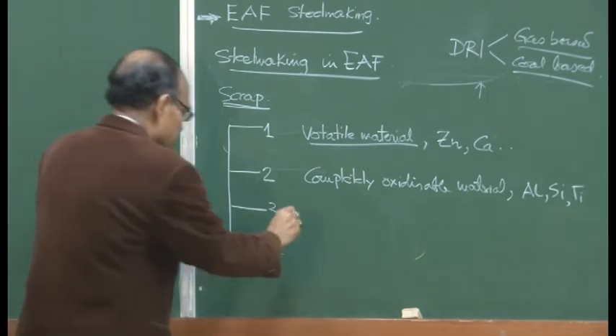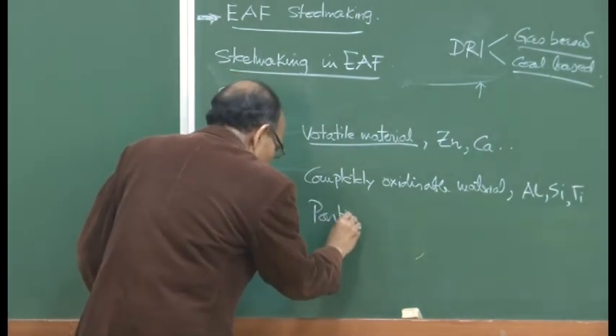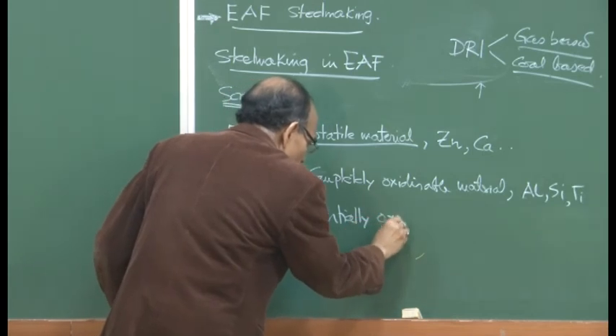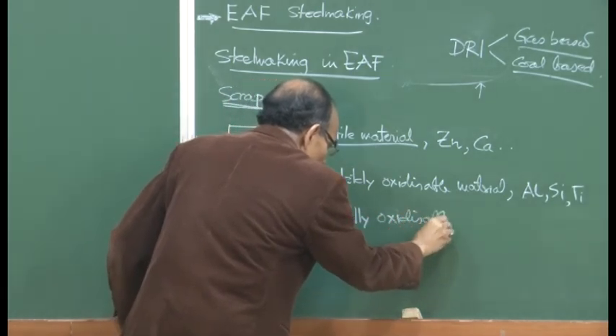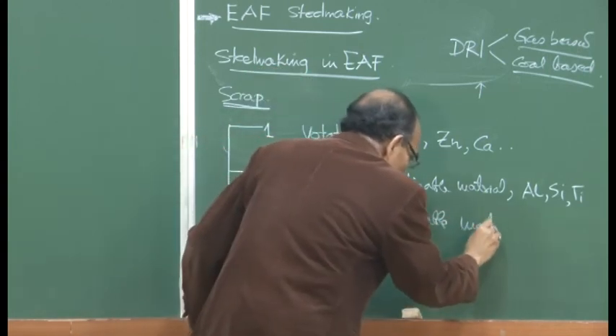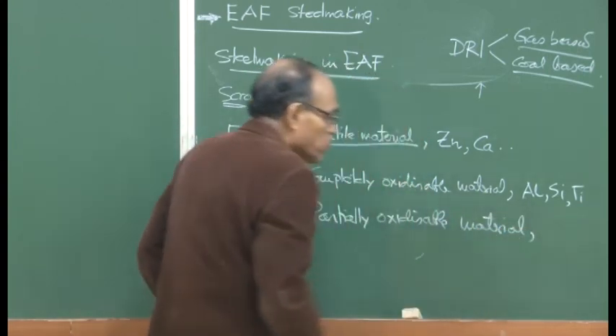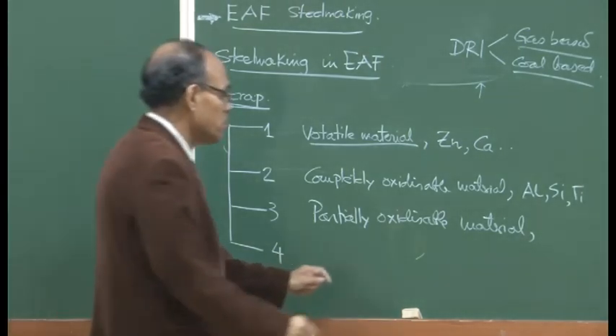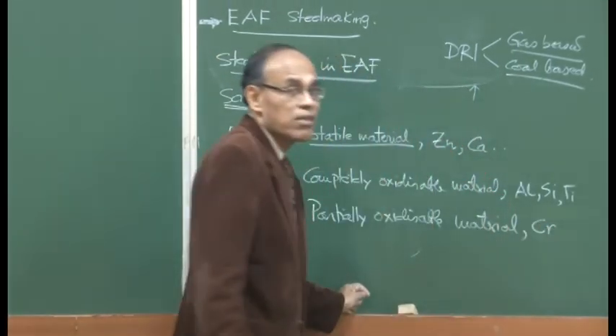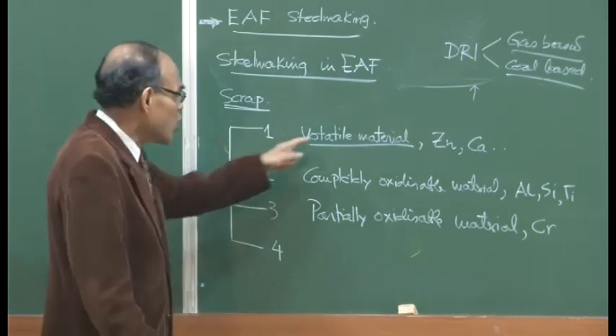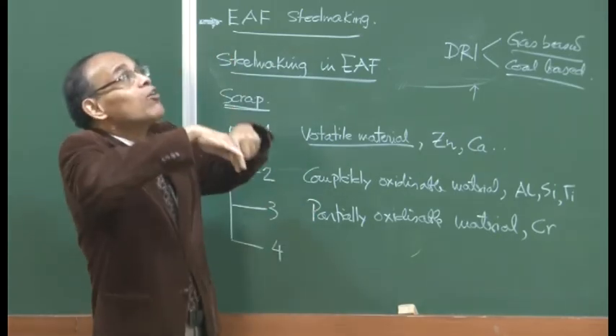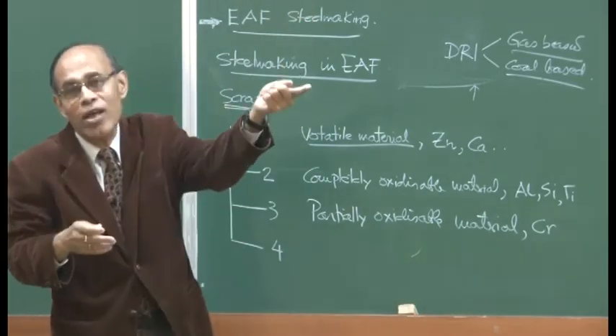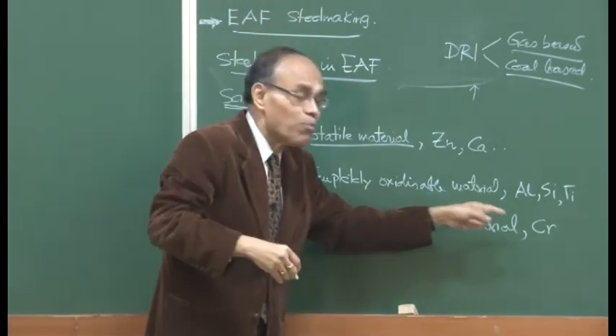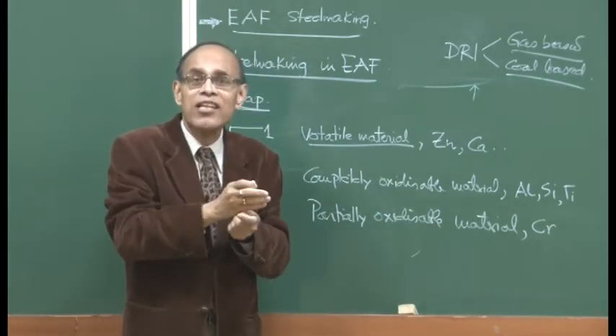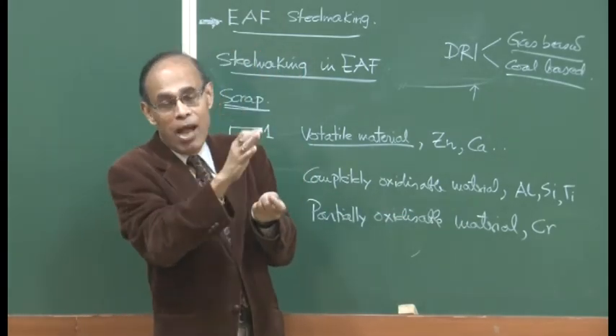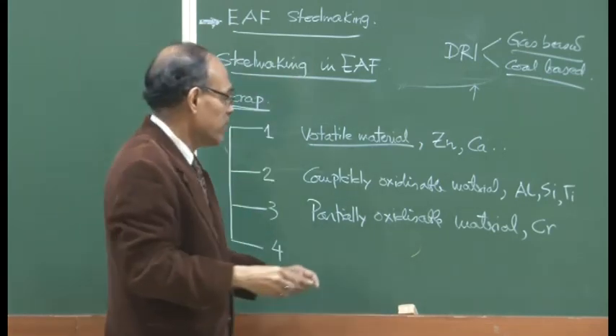Partially oxidizable material, elements such as chromium. That means partially oxidizable material will oxidize, they are not volatile. So, if they are not removed to the gas phase, where will they go? They will go into the slag phase. So, partially oxidizable material such as chromium, and if phosphorus is there in the charge, phosphorus will also partition. Some will remain in the metal and some will go into the slag.